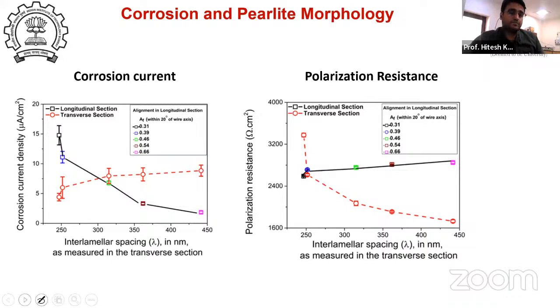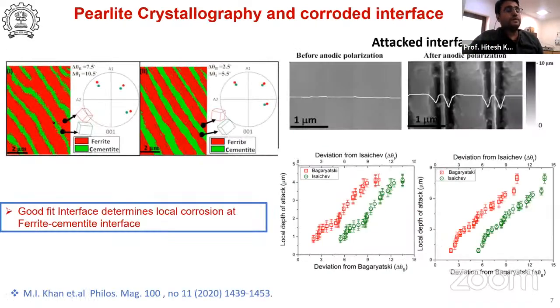The question arises why it is happening. Because the interlamellar spacing is in nanometers, we can't do EBSD on the fine pearlitic colonies. So we thought, let's grow some coarse pearlitic colonies at laboratory scale with slow cooling. We grew some coarse pearlitic colonies and marked those colonies with the help of micro indents, and did EBSD on that. For the same reason, we corroded it in the H2SO4 solution.